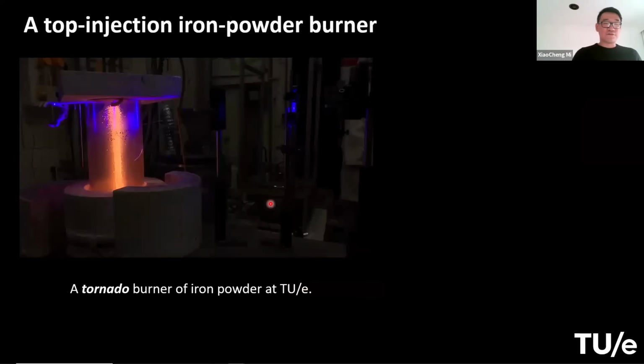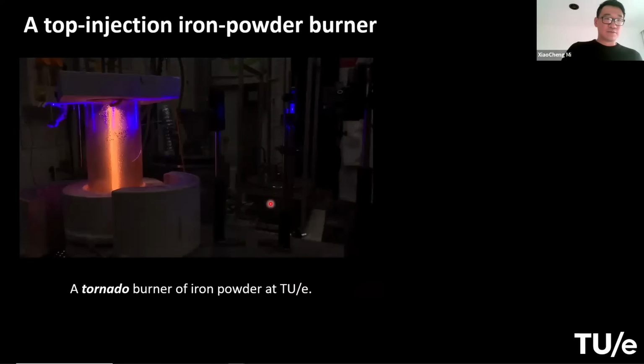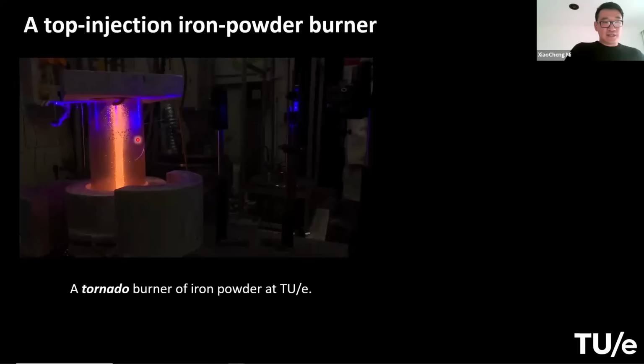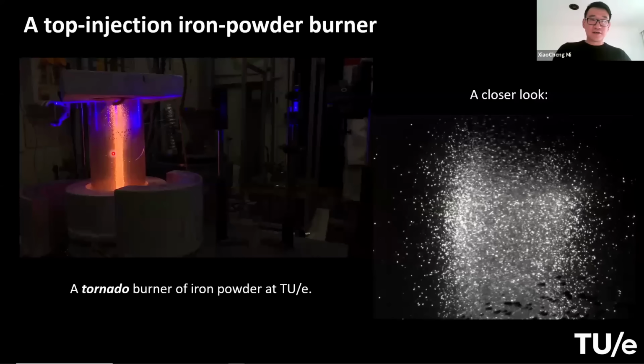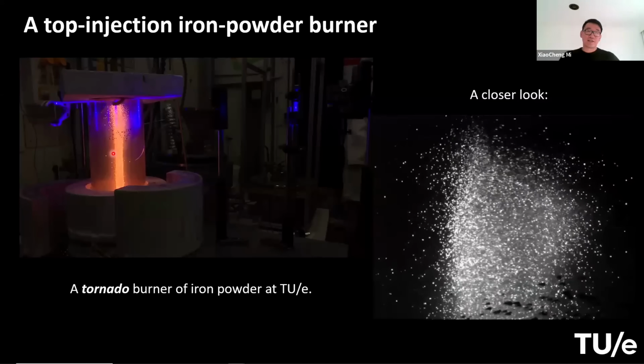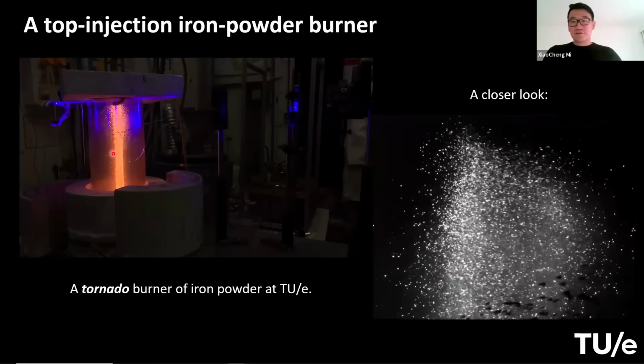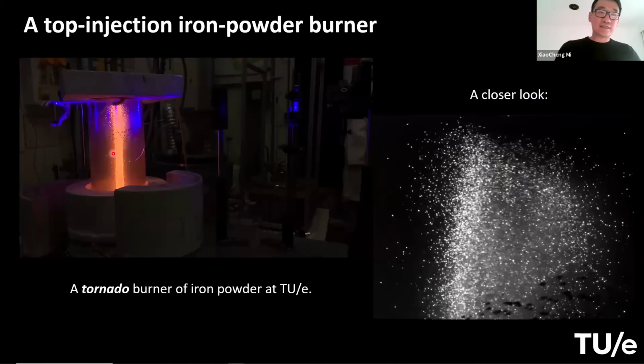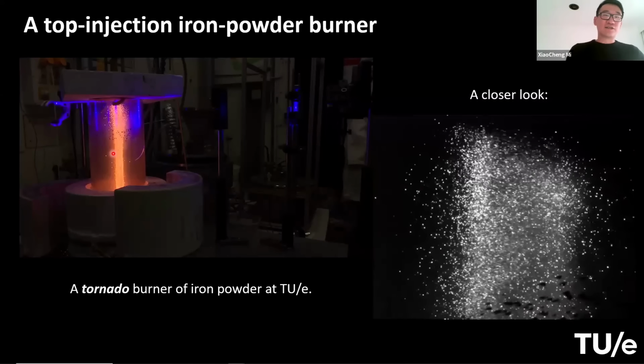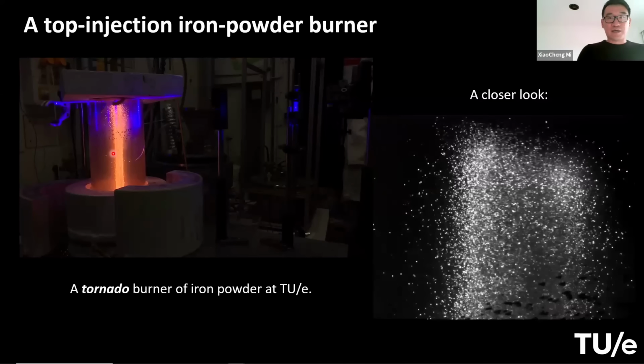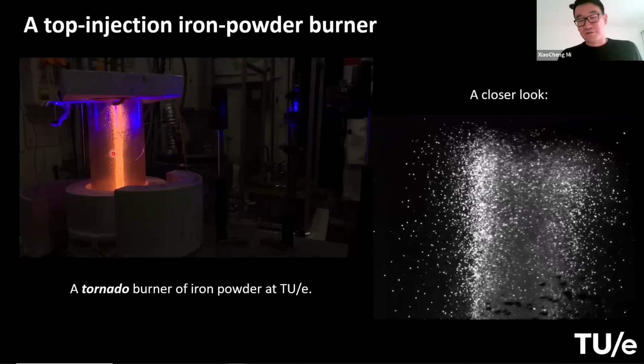The later idea is the top injection iron powder burner. So you inject iron powder from the top, and there is also a swirl generator on top of this burner, and it makes a swirl inside this cylindrical chamber in such a way that iron powder moves in this tornado motion, which you can have a closer look at here. In such a way, the residence time of the iron particles can be increased, so they have enough time to combust and release the heat to ignite the later injected particles. So you can maintain the flame without any other fuels in there.